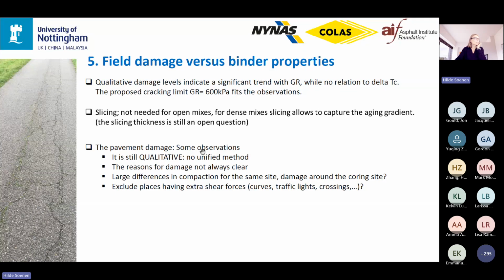Then some other observations. So we still use the qualitative damage level, because there was no unified method used by the road authorities. And even if you have the damage, it's not always sure what the reasons are or where it comes from. Very often you can determine it from the crack shape, but not always. We also noted large differences in compactions for the same site. So therefore, we focused a little bit more on the damage around the coring site. And we also excluded places having high shear forces like curves, traffic lights, crossings. So we looked more at the straight parts in the sections.